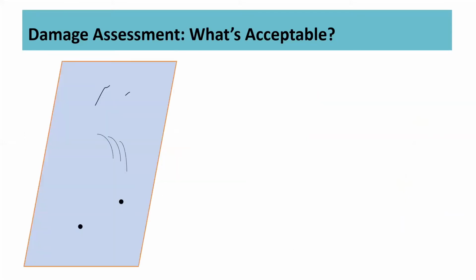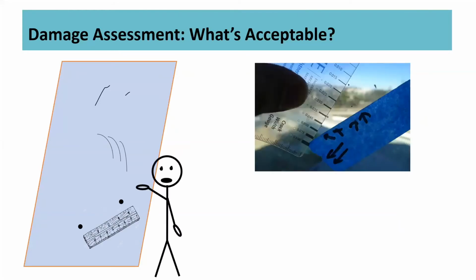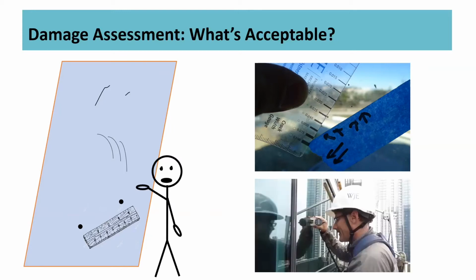The next step would be to measure those blemishes. In the upper right-hand corner, you can see we're measuring the diameter of a point blemish. And then we also measure the distance between the point blemishes, because that is part of the criteria of the standard. For our own purposes, we also try to measure the depth of the blemish, because that will give us some idea as to how much glass polishing might be required to remove the blemish from the glass surface. And we have some experience on past projects, and it would tell us whether or not we believe it will be a promising exercise to try to polish that scratch out.